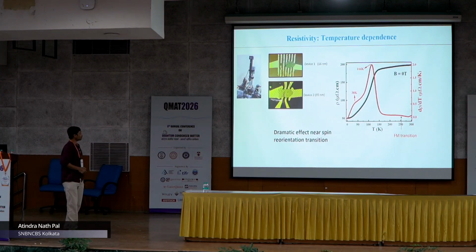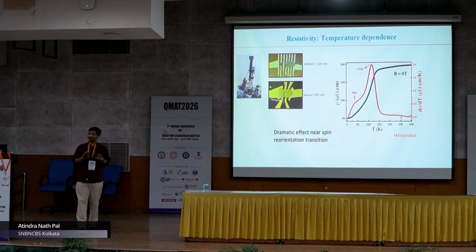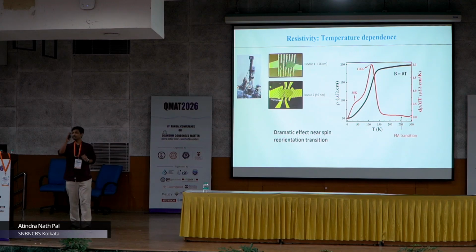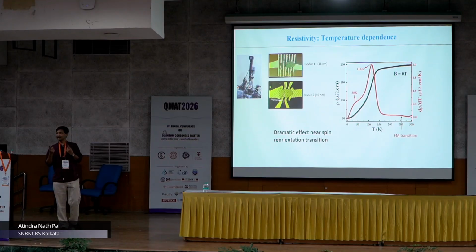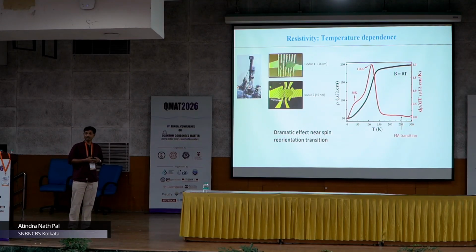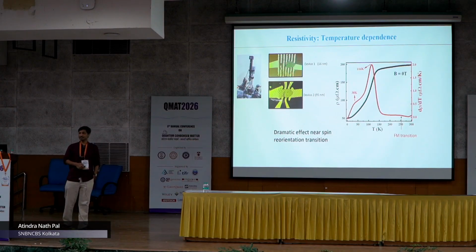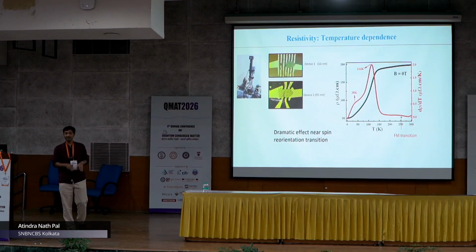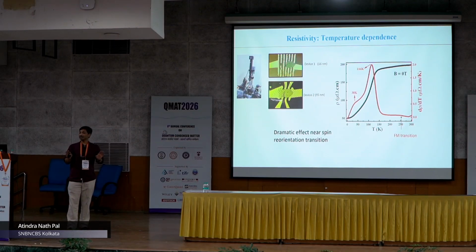First of all, these materials, like in the previous talk you heard about WTe2, are fine in the bulk limit. But when you go to the device limit, when you are exfoliating, these materials are very difficult to contact, like getting electrical contact is actually difficult. So we have developed this heterostructure dry transfer setup, and if we just do lithography and all this, then we will not get any contact on the device.